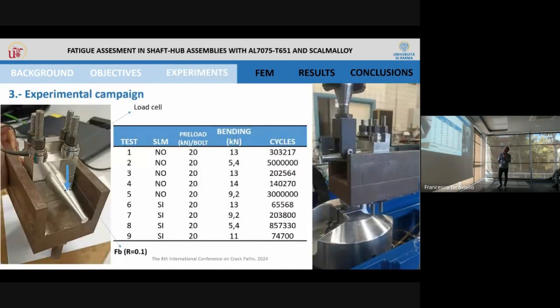So let's start with the experimental campaign. To do that, we designed a specific rig only for this type of test, in which we apply a normal load to the shaft instead of reproducing the internal pressure by the interference, in a more controlled way. We thought that with these 4 bolts that are instrumented with a load cell, we can better control the pressure produced at the contact zone.